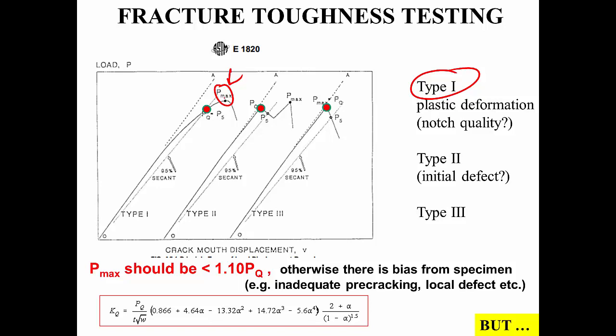But to make things consistent and more proper for the calculation of the fracture toughness, the custom is to take a slope that has 95% of the slope of the initial elastic part, and the intersection of this 95% slope with the force opening curve, we call it P5, I guess, for the 5% difference from the initial slope. And in the case of plastic deformation and substantial nonlinearities in the curve, that is exactly the load that we take as the maximum load of failure.